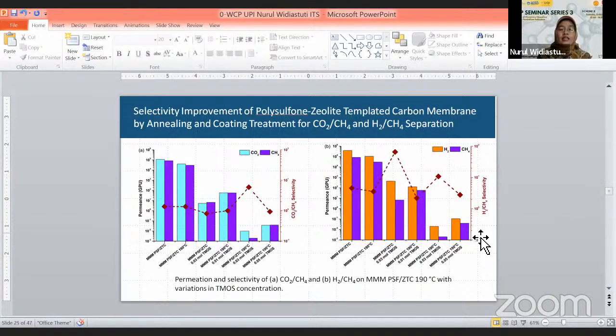As we see here, in the gas pair of hydrogen and methane selectivity, we found that some of the membranes already achieved the permeability and selectivity based on the Robeson curve, above the curve over here. It means that the membrane's performance for gas separation is potentially usable, especially for hydrogen and methane separations.